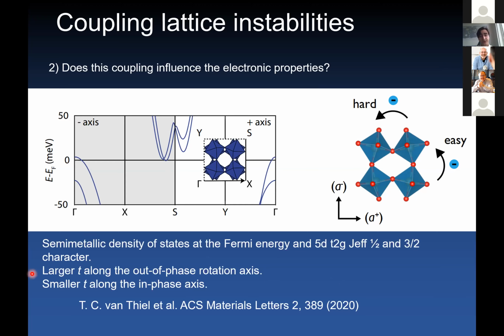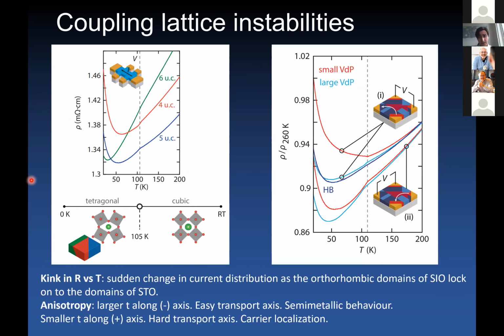And the result is that along the out of phase axis of rotations, your wave function will experience a larger hopping parameter, while along the in phase axis of rotation, your wave function will experience a smaller hopping parameter. So this explains naturally our experimental observations. So the kink in the R versus T is caused by a sudden change in current distribution that occurs at 105 Kelvin, at the moment in which the orthorhombic domains of strontium iridate lock to the tetragonal domains of strontium titanate, with this special 45 degrees domains.